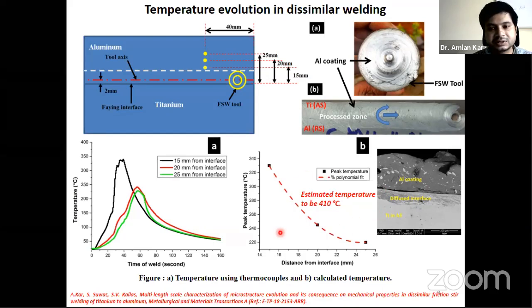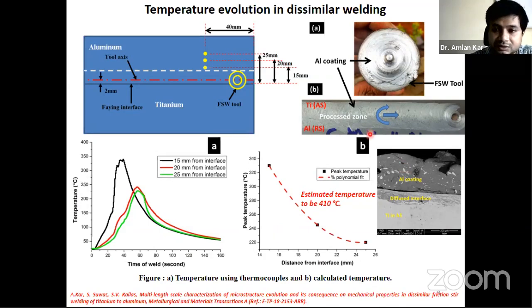Why have we taken the edge of the shoulder? Because we are assuming that the temperature developed below the shoulder is uniform. There are two aspects there. The first and most important is the recrystallization, and the other is that the friction value is not overall constant, and we think it is close to the sticking friction. Due to the sticking friction, you can see here that aluminum is actually sticking to the plate as well as the tool. And this is clear information of the sticking friction being very, very active.